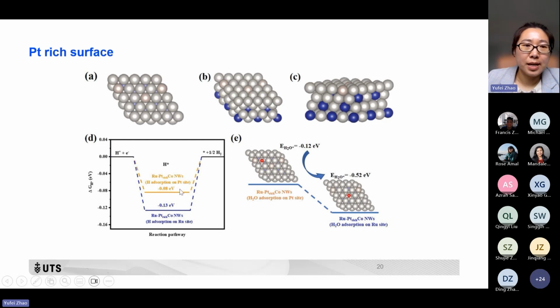We have calculated the hydrogen adsorption energy on the ruthenium and on platinum. We found the platinum has better absorption energy compared to the ruthenium. So on this platinum-rich surface, the platinum site should be the active site for the hydrogen adsorption.